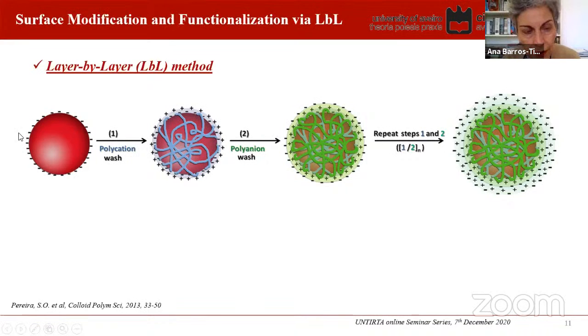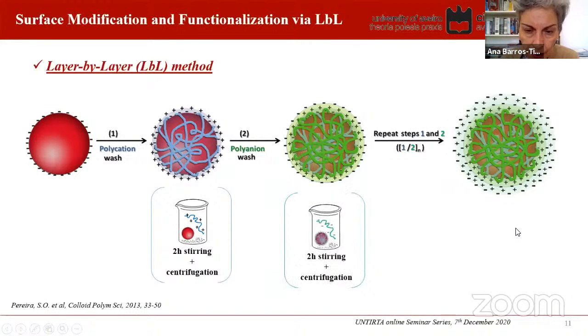So in the layer by layer method, we basically have the gold nanoparticle, and then we alternate the deposition of a polycation, wash, get the charges on the surface changed from negative to positive. And then we immerse these nanoparticles or add these nanoparticles to a polyanion, wash, and again the surface charge is changed. So we can repeat this a few times and increase the size of the shell. This was actually done with some polycations and polyanions, and it was reported.